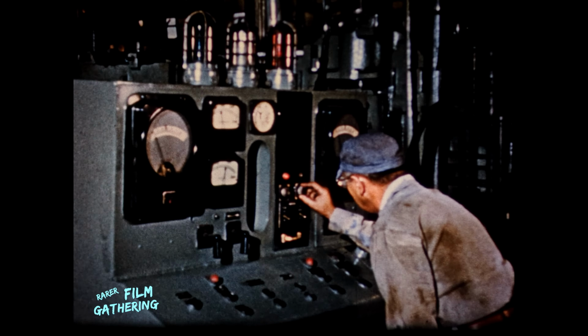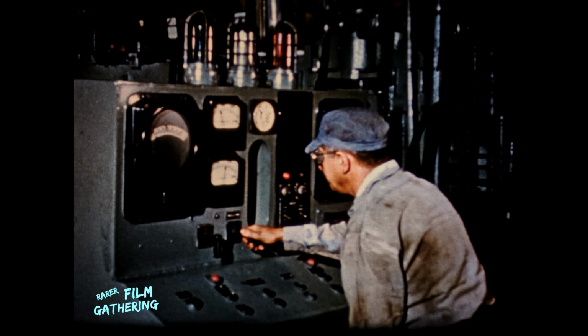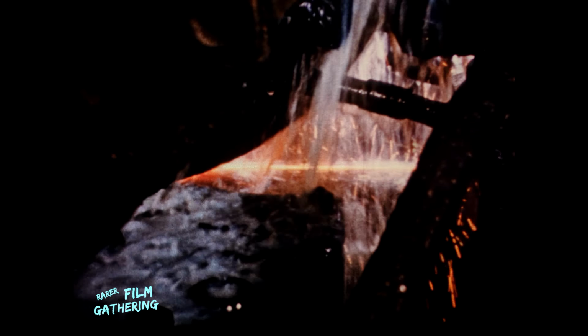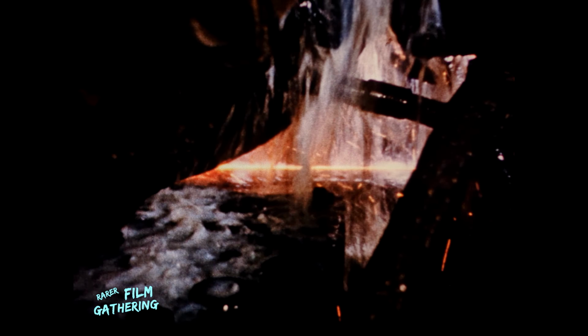Electric resistance welding was pioneered by Republic in 1928, and we've been producing it for over a quarter of a century. With all this experience, we've developed a precise control over time, temperature, and pressure that must be achieved to produce a uniform weld that is as strong as the parent metal. What is done is this: raise the edges to a welding temperature and then force them together under pressure. No metal is added. The weld is formed entirely of the parent metal. It's all automatic. Everything is controlled to give both a fine ductile condition with the least variation in the grain structure. Here's a diagram of it.